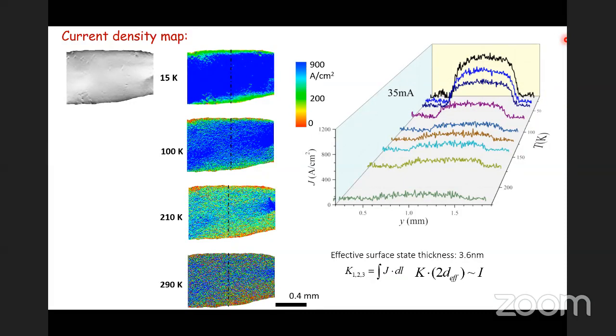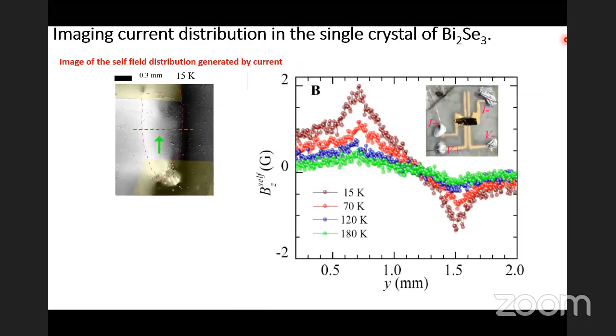So we analyze this, and where is the current going from the surface then? We analyze the field distribution. If you look at the magnetic field distribution on the surface in this self field, at low temperature, this is the field distribution. But as you increase the temperature, the field distribution actually becomes more and more flattened and spread out while you are measuring the sample.